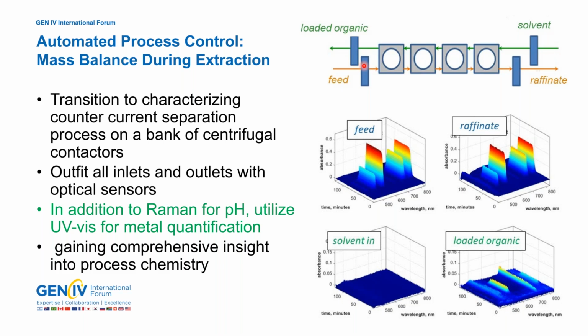The rectangles that I have shown here in blue represent the locations on our centrifugal bank of contactors where we had UV-vis and Raman probes to measure in real time what went into the contactor in the feed, what came out in the raffinate, what went in the solvent, and what came out in the loaded organic phase. What I have shown down here are the spectra taken in real time of the UV-vis for the feed location, raffinate, solvent in, and the loaded organic.